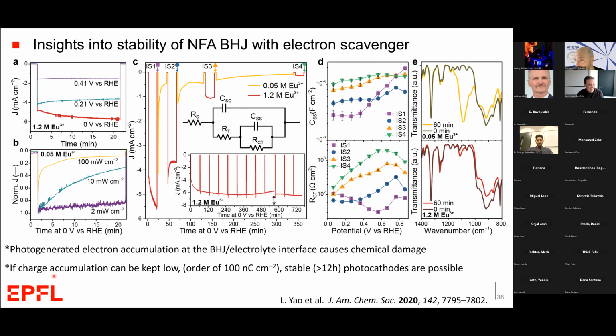We know that if we can keep the charge accumulation low, on the order of 100 nanocoulombs per centimeter squared, that we can achieve good stability with the performance of these photocathodes. So reducing charge accumulation means that we have to put a very effective catalyst that can drive the hydrogen evolution reaction on top, and also make sure that that catalyst is well coated and well adhered to that organic film.